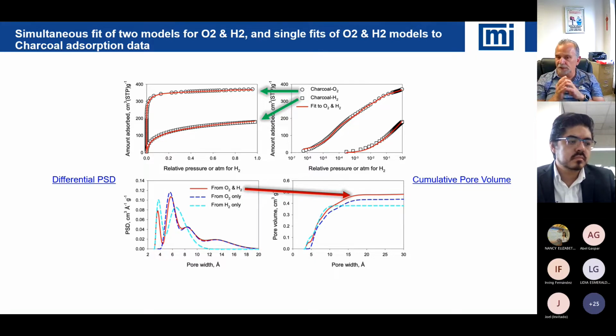When it gets to a larger size, we don't have the same good contact with the glass like you typically would during a measurement. So it takes a little bit longer to remove the heat. Even with fine powders, if you use a very large bed and it sits in sort of a pile, it will slow down the equilibrium. So that's one consideration: perhaps a bit more patience associated with how long to conduct the experiment.